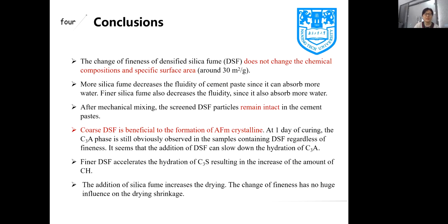Densified silica fume is beneficial to the formation of AFm crystalline. At 1 day of curing, the C3A phase is still obviously observed in the samples containing densified silica fume, regardless of fineness. But it seems that the addition of densified silica fume can slow down the hydration of C3A. Finer densified silica fume accelerates the hydration of alite, resulting in the increase of the amount of calcium hydroxide. The addition of silica fume increases the drying shrinkage, but the change of fineness has no huge influence on the drying shrinkage.